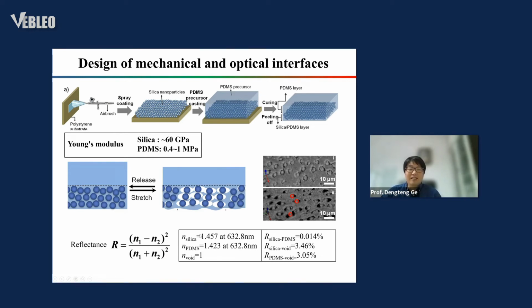To design this membrane, we found silica and PDMS have a similar refractive index. So when put together, it's totally transparent. But the mechanical Young's modulus is totally different. For example, silica is about 60 GPa, and PDMS is less than 1 megapascal. So when we stretch them, a new interface will be generated.